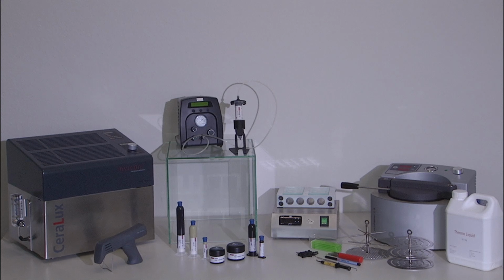After curing, and that is also very, very important, there is an inhibited layer. Always, if you cure light curing material in an oxygen atmosphere with a blue light, you will get an inhibited layer. What is this inhibited layer? It's like an oily film on top. And this oily film could make some problems in the process after applying. So that means we don't want this oily film on top. That's why we remove this oily film with a sponge.